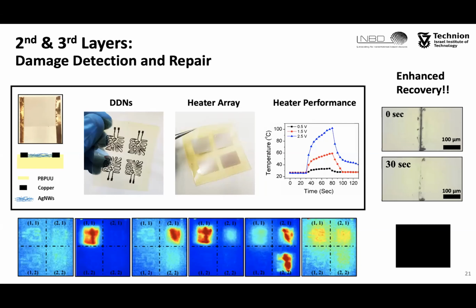The heaters were composed of a silver nanowires network embedded inside the polymer, and this heating-induced repair process led to healing of superficial cracks in just 30 seconds, instead of 24 hours as in the previous polymer, or in 5 minutes in the case of really heavy cuts or damage, which otherwise in the previous polymers we couldn't achieve even after 48 hours at 70 degrees Celsius.